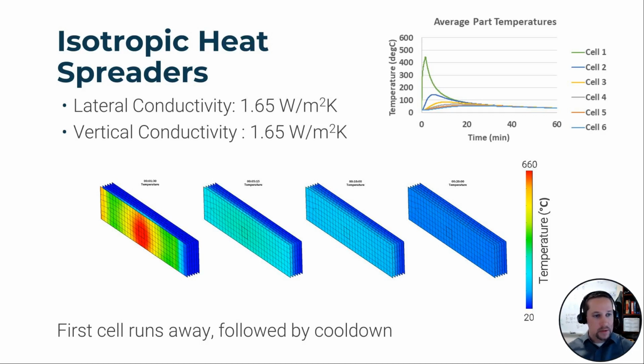So we looked at another case of isotropic thermal conductivity, which was the average of the in-plane and through-plane conductivities. So this is 1.65 watts per meter Kelvin. And when we increase the conductivity, such as this, in this case, the first cell runs away, followed by a cool down period. So this predicts that we have less thermal runaway propagation, and that could be dangerous, particularly when you're looking at cases with more cells and higher heat rates, or possibly more energy dense compositions inside the battery. You don't want to predict a safer situation than you would expect to see in a vehicle.